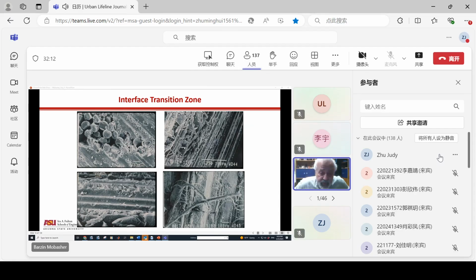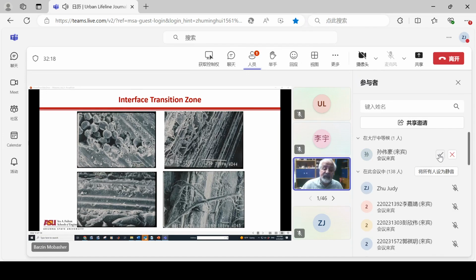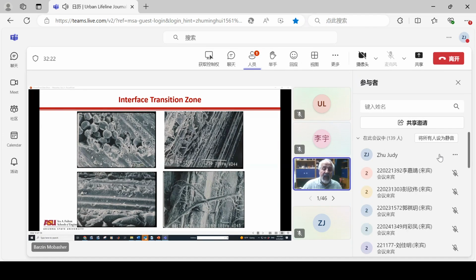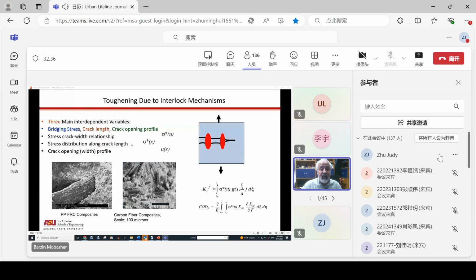bond. And I want you to pay attention. We don't get full bond in these cases, and that's okay because these weak bonds give us delamination, cracking. So I don't want perfect bond actually, because perfect bond would mean that the crack has no propensity, has no direction to go up and down and in different directions. I want damage. I want these to be directing the cracks. And that is obtained by these interlock mechanisms that we have.